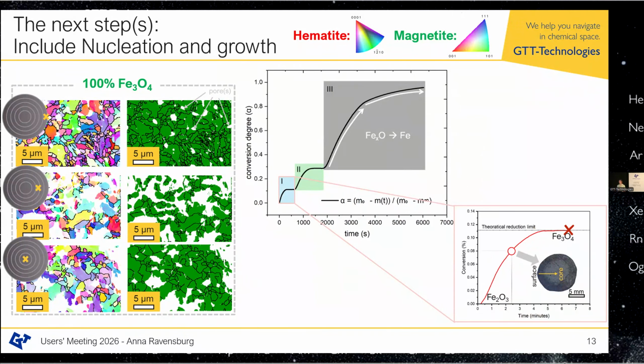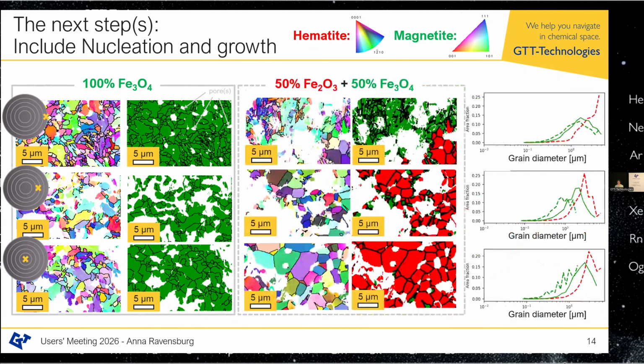And we can not only do this for 100% conversion, we can also do this, for example, for 50% conversion. And there it becomes interesting. Again, please look at the green and red plots. Because here we see a distinct difference between the core and the surface. At the core, we have mainly still Fe2O3. We have very big grains, and we have some nucleation sites of Fe3O4. The nucleation happens at the pores, which makes a lot of sense because that's where the gas goes through.